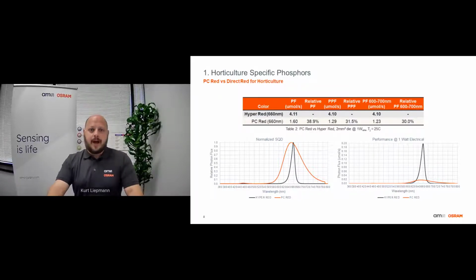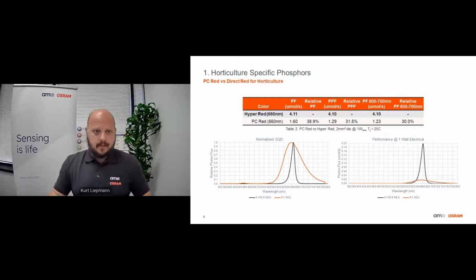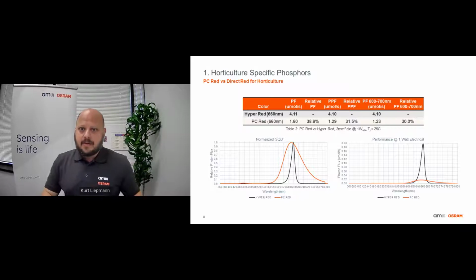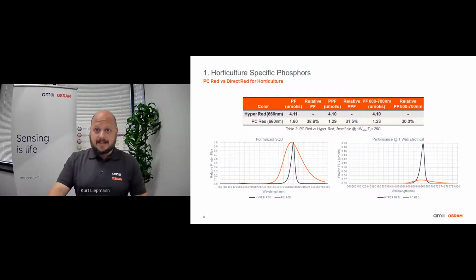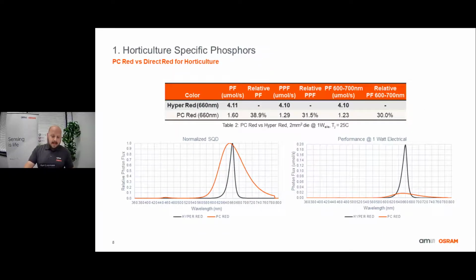So I just showed you how inefficient it is to generate red photons through down conversion. So how does that compare to a direct emitting 660 nanometer red LED? So same conditions as before, we can see that a phosphor-converted red LED emits less than 40% of the photons of that of a direct-emitting red LED. And if we look specifically at the red photons between 600 nanometers and 700 nanometers, its relative output is even less at only 30%.